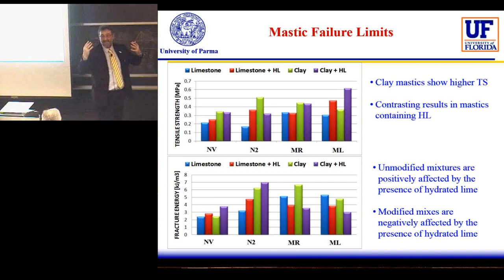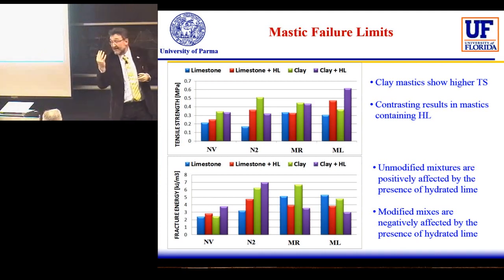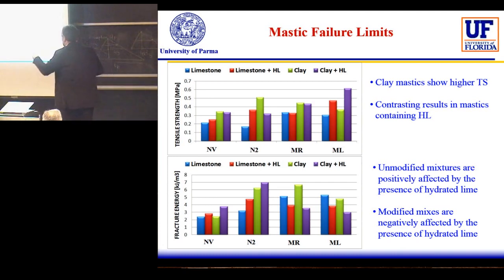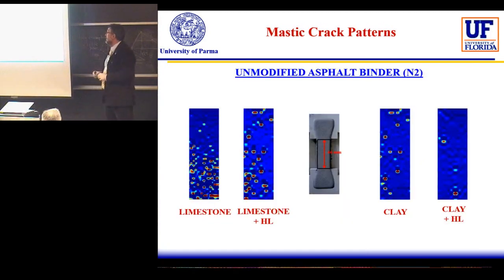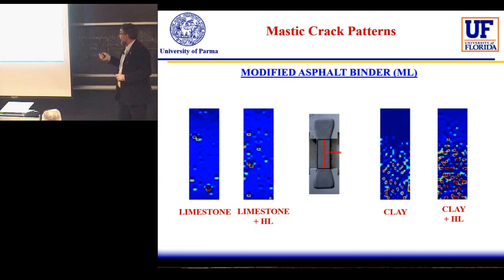So this is just an analysis of what happened, but what is clear is that for sure the fracture energy and the tensile behavior of the material are strongly influenced by the filler. And again, if we look at the crack pattern, we clearly see different behavior as a function of the different mineralogical properties of the filler, affected by the presence or not of the hydrated lime. Again, this is something seen only on the mastics.